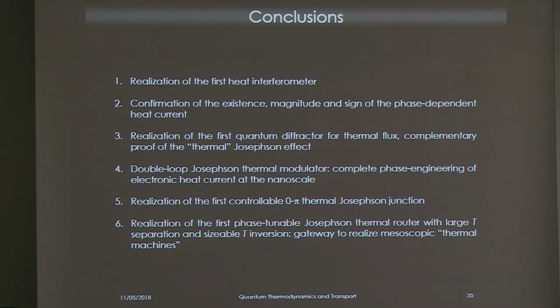Okay, so I will go to the conclusions. Apart from giving the main concept of the phase control of heat, we have shown the realization of the first heat interferometer that has confirmed the existence, the magnitude and the sign of phase-dependent heat current in Josephson systems. Then we have shown the realization of the first quantum diffractor of thermal flux, which sets the complementary proof of the thermal Josephson effect in this kind of system. Then we have shown how double-loop or multi-loop Josephson thermal modulators can ensure a complete phase engineering of electronic heat current at the nanoscale.